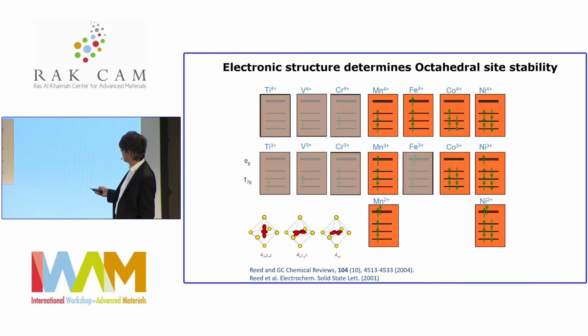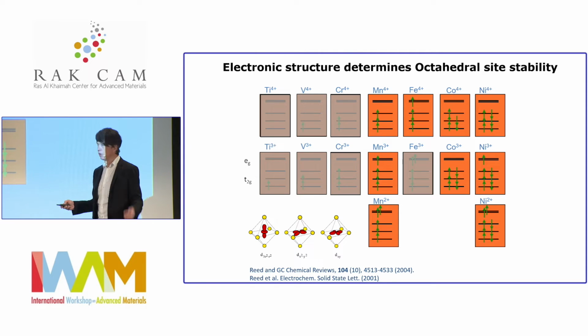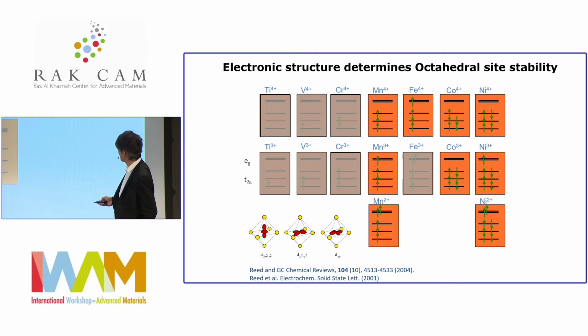The other thing is chromium disproportionates to chromium-6, and that's highly mobile. Okay, iron is terrible. Iron 3 plus, 5 electrons, is basically a spherical ion, wants to go all over the place, and so you can't use that one either. And then manganese is bad, if I can use the pointer. There we go. Because manganese 2 is also a spherical ion, same electron configuration as iron 3, and manganese 3 tends to disproportionate to 2 and 4, so you can't use that either.